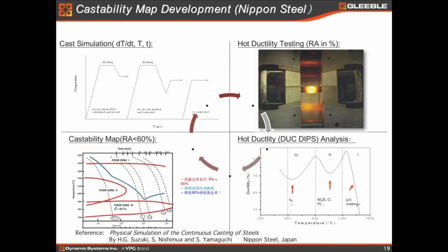So coming back to low ductility region 2, they found easily from the SEM that it's the non-metallic inclusions that caused the problem, because they are segregated into the grain boundaries. So when you have deformation there, it's going to crack, right? That is why clean steel is the goal. It's become very usual now, but at that time it was not. It's still the goal. You've got to make your steel much cleaner, because if it's not clean, you have a problem.